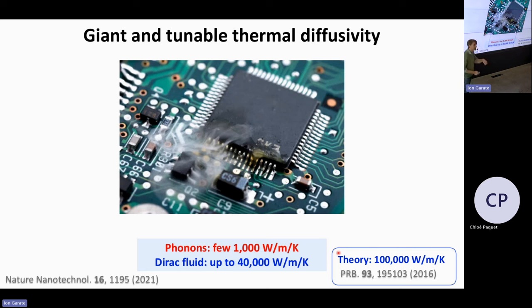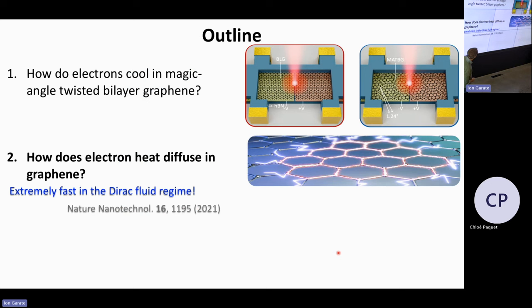If you have hotspots, very tiny hotspots, if you can have some graphene there that spreads out this heat very fast over at least a micron or so, you can avoid the breakdown that happens because this hotspot starts getting even hotter and eventually breaking down your device. So that's something we're studying now more from an applied perspective.